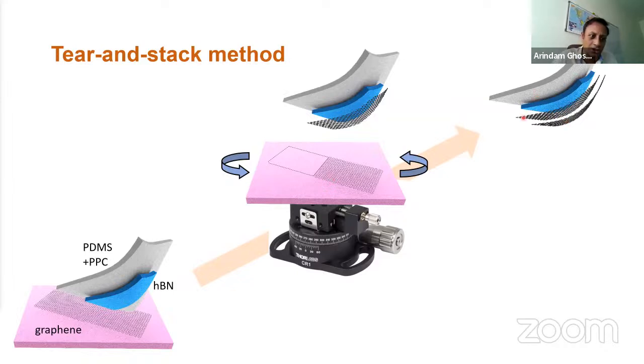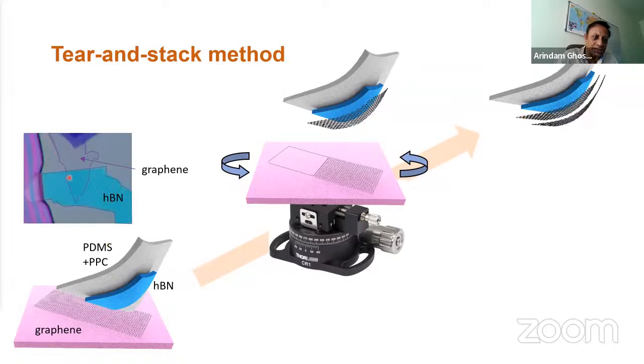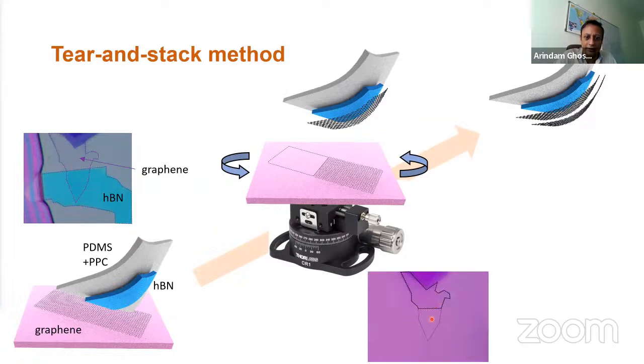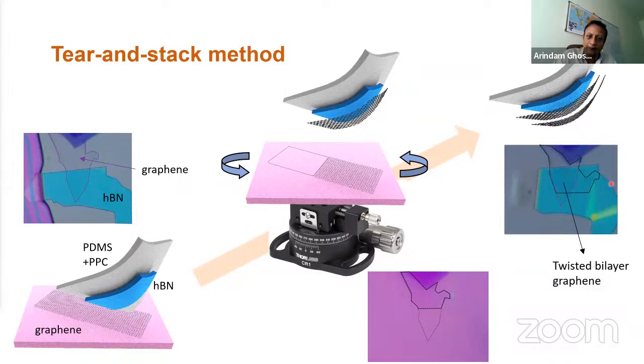If I show you the actual image of a device, this one is the graphene, and this was a layer of boron nitride. You press the boron nitride on the lower graphene, and then you lift it up so that the graphene gets cut along the edge of the boron nitride. Then you shift and rotate it, and you essentially get the new system, which is the boron nitride with the twisted bilayer graphene underneath, at the angle that you have set. So our experiment is this: we pattern these twisted bilayers using electron beam lithography and put on electrical contacts.